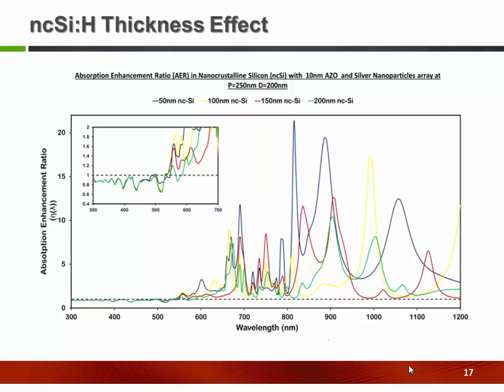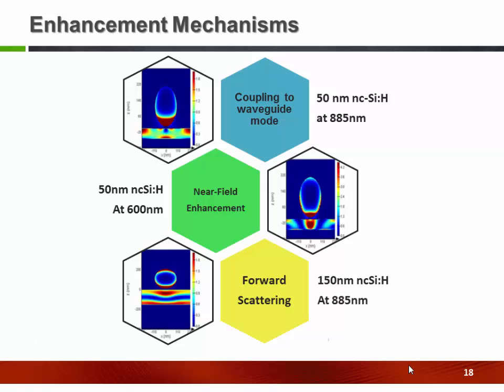The other parameter that I have investigated was the thickness of the absorber layer, from 50 nanometers to 200 nanometers. And I have seen that by decreasing the thickness, normally I could get a higher performance improvement. For example, 50 nanometer nanocrystalline silicon shows higher improvement if I use the same nanoplasmonic structure on top, with respect to 200 nanometers. This depends on the waveguide modes inside each layer and the mechanism, which is related to the coupling of the incoming light to these waveguide modes.